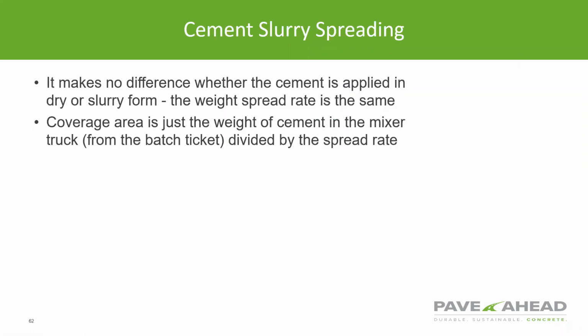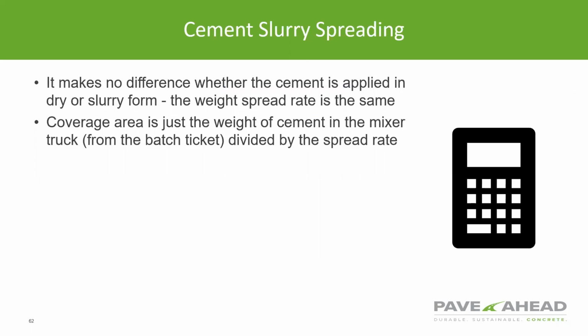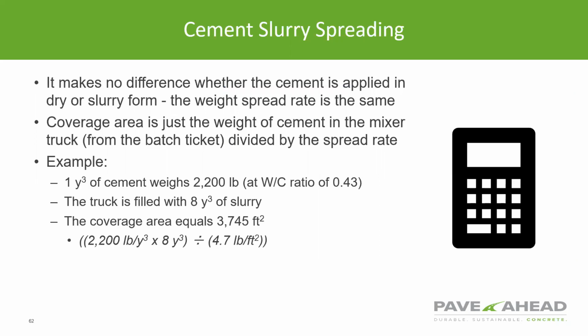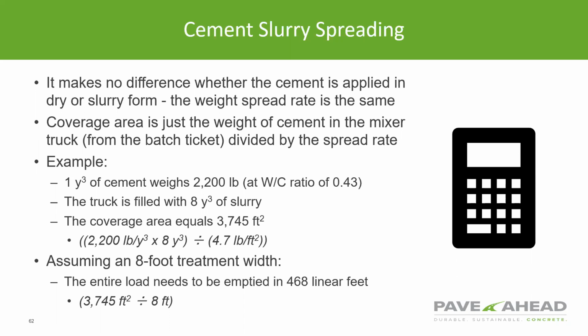And it really makes no difference whether that cement is dry or in slurry form. What we're concerned about is the weight of that cement. So for an example, let's say we use that mix design that provides 2,200 pounds per cubic yard, and we got 8 cubic yards of material. We would divide 2,200 times the 8 cubic yards by that spread rate, and that's going to give us the area, the 3745 square feet.